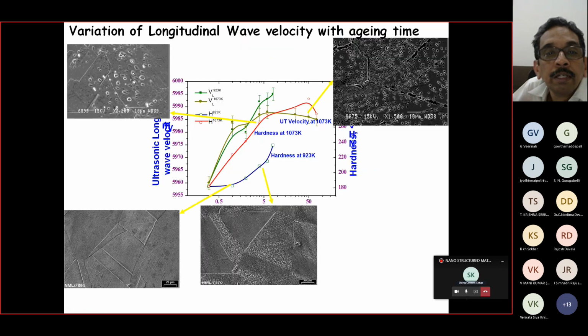With this particular technique, I was able to show that if I have a material with a particular nanostructure of precipitates inside, the hardness changes like this. You can see it is increasing to a particular extent, and after a particular time, the x-axis being the number of hours, it is decreasing. If you see the velocity, this light green line, it is also following the hardness. So in a non-destructive way, I was able to confirm that if I heat treat a material at 1073 degrees for 50 hours, I can get a nanostructured material, which is seen in this SEM picture, and the mechanical properties are also changing, which is reflected through my ultrasonics.